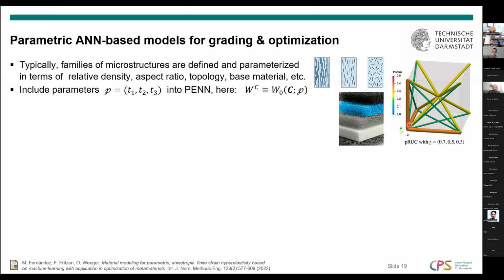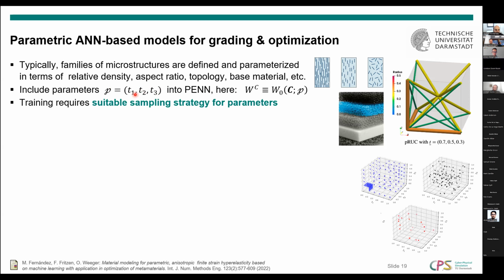And here we apply this now to these beam-like microstructures, where we basically combine three different topologies. The orange one with struts on the edges, the green one with struts on the faces, and the yellow one with struts going through the center of the cell. And we scale now the diameter or the radius of these three topologies using a certain parameter. So basically we have three design parameters. If all radii or all diameters were 0, then we would not have any structure. But if one of them is non-zero, then we have a certain microstructure.